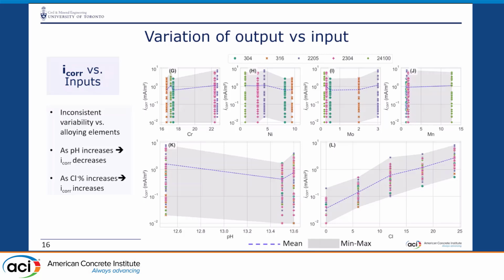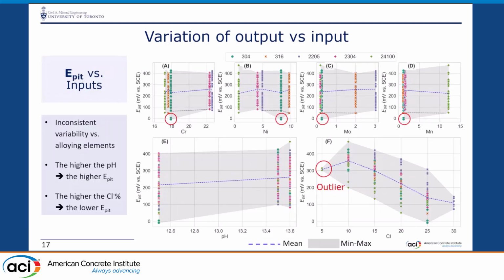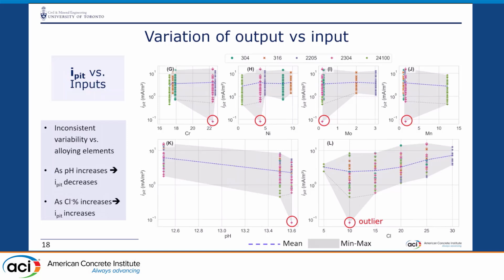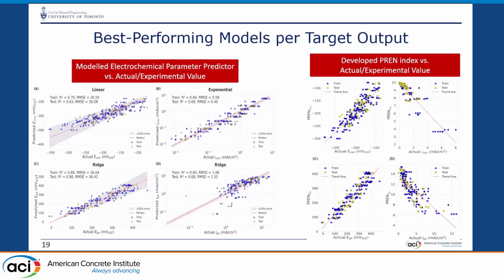Corrosion current is very similar for all of them. They go in a straight line, with no major increasing or decreasing trend. But again, it's clear for pH and chloride. If you look at pitting potential, something similar. If you look at pitting current density, it's the same. But these are experimental data based on commercial stainless steel alloys, which makes it very difficult to isolate the chromium from the molybdenum, from the manganese. Just repeating that so that it's clear what the challenges were.